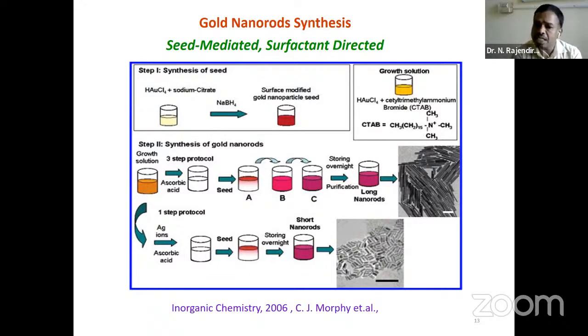How it forms: we know that the surfactant at the CMC exhibits a spherical nature. Okay. So upon increasing above the CMC, what will happen? The spherical surfactant structures join together in the form of cylinders, where the interior provides a site for the growth of the nanoparticle, so that when you add the seed solution and the growth solution, these metal ions are reduced inside the template and form rod-shaped particles. Further, we can confirm by transmission electron microscope that the synthesized particles are all uniform in rod shape.